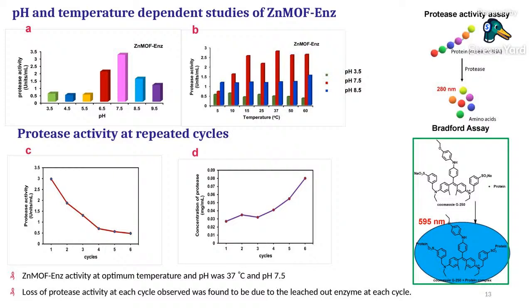Because if I want to use it in Rajasthan during the summer, the temperature will be around 50 degrees. So how does the temperature impact the enzyme activity? What we saw is that it is pretty much not impacted by temperature from 15 degrees to 60 degrees. But pH, yes, it has an impact. So we kept the temperature at 37 degrees, which is the temperature we have in Chennai. Then we took pH 7.5 and a temperature of 37 degrees.